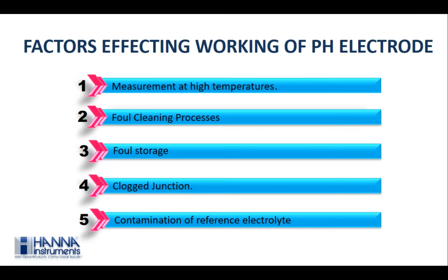Similarly, a clogged junction and poor cleaning processes go hand in hand. Poor cleaning or no cleaning practices lead to a clogged junction, which leads to sluggish readings and very slow response, as there is no space for the electrolyte to come in contact with the sample, hence lowering the electrode performance. Contamination of the reference electrolyte solution takes place as the solution being measured is allowed to migrate through the junction, entering the electrolyte cavity, thereby changing its composition and altering the electrochemical reaction completely.